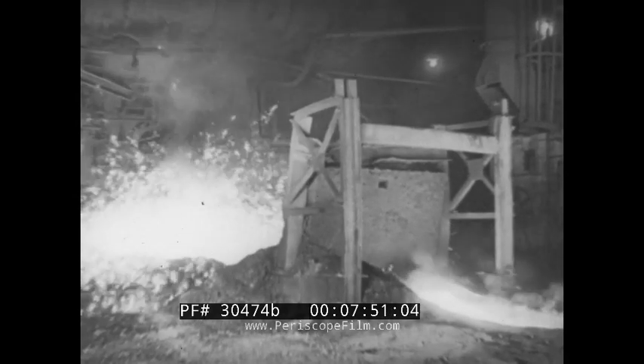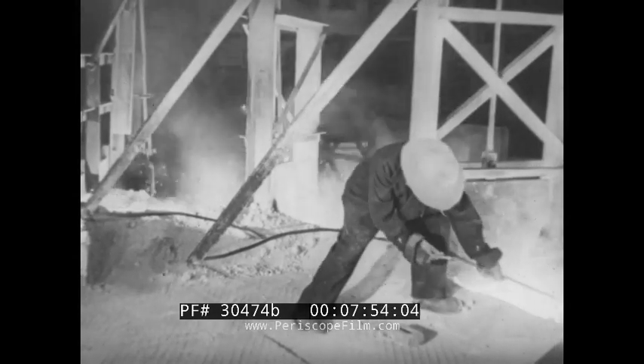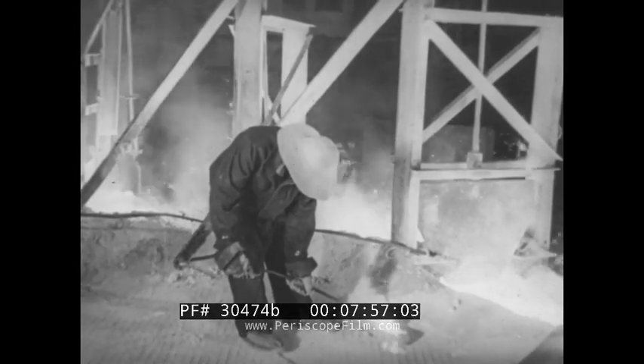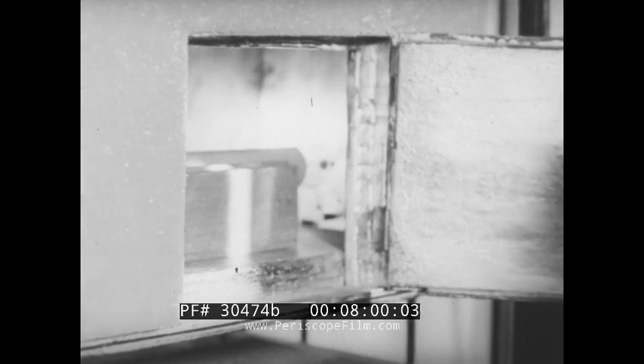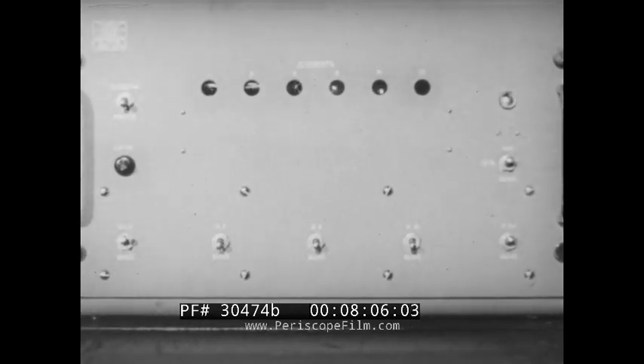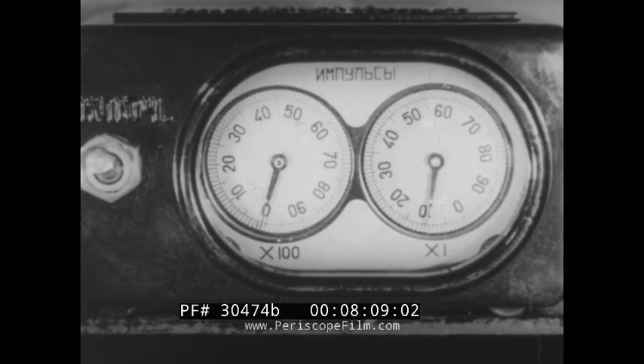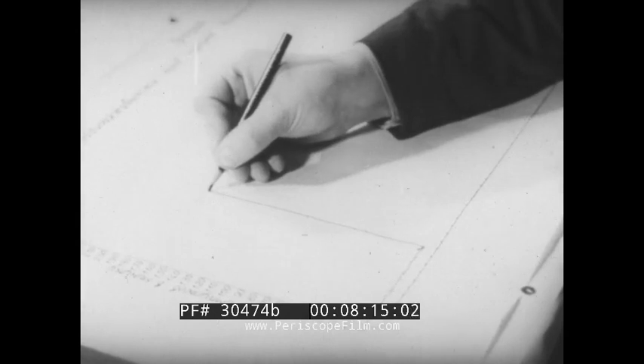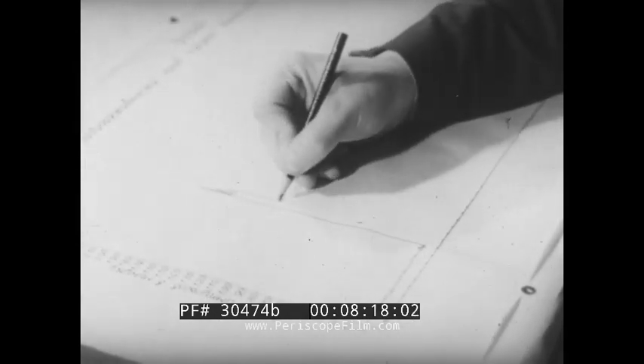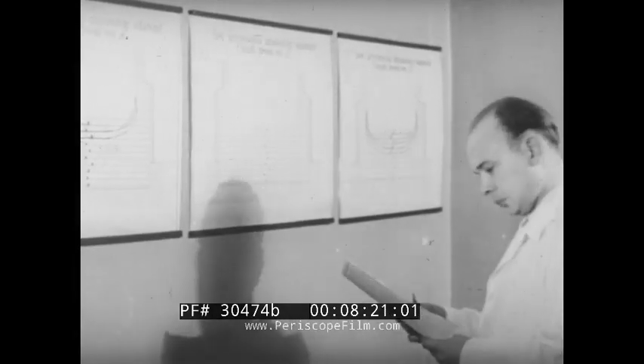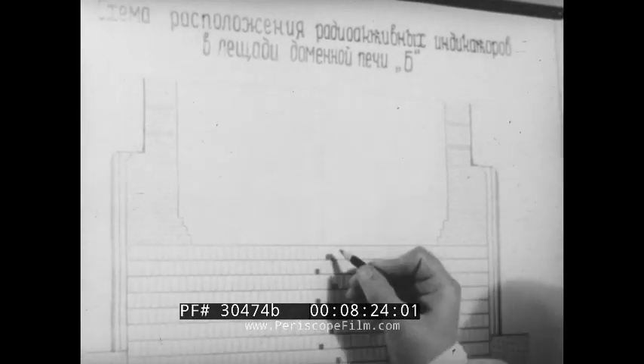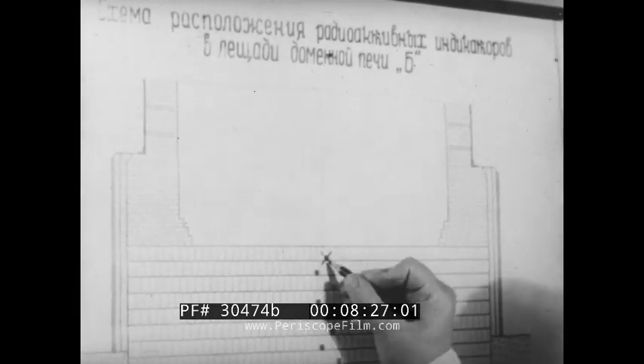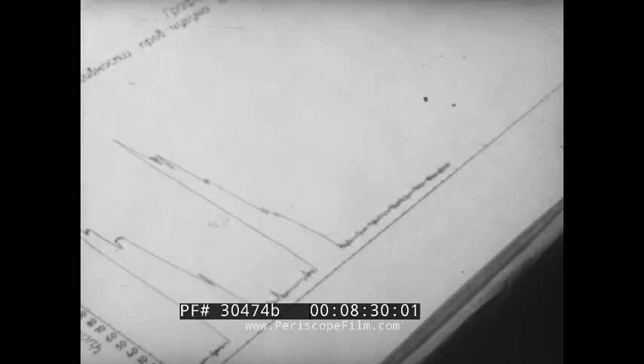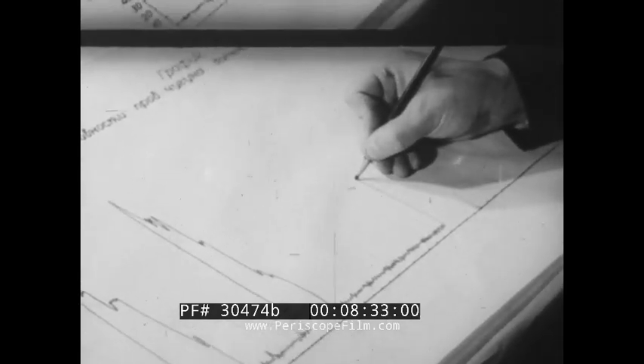The blast furnace continues to operate. Again, samples are taken. And again they are tested. This time the instruments detect a certain radioactivity of the metal. We now know that the first ampule has melted and the radioisotope is mixed with the metal. That means the top layers of the hearth have been destroyed. In this way, tracers can be used to follow the destruction of hearths in blast furnaces.